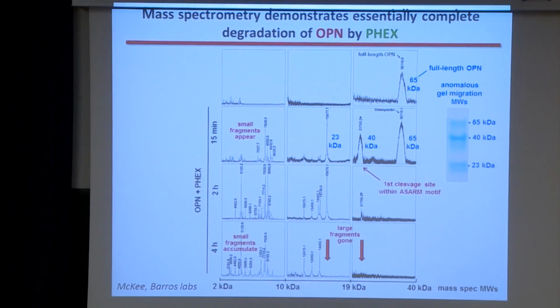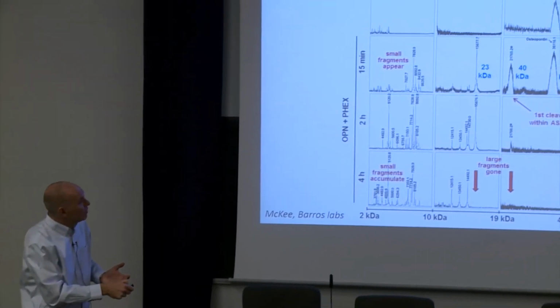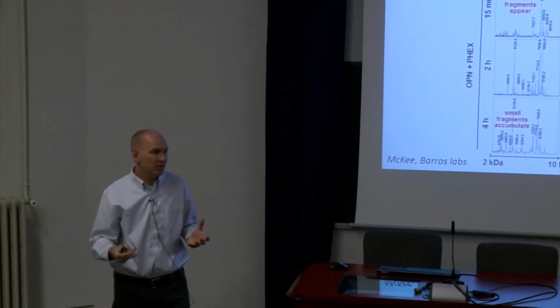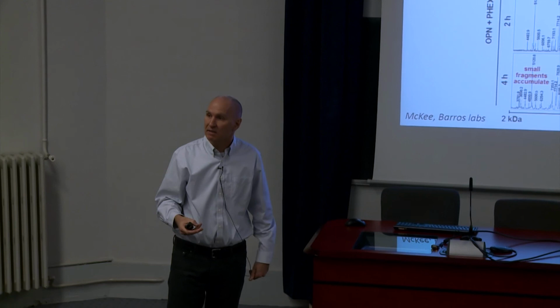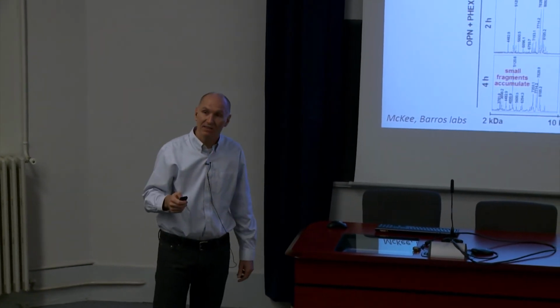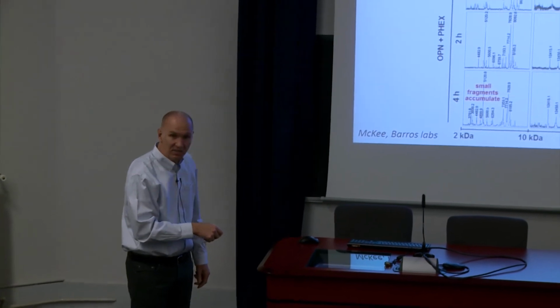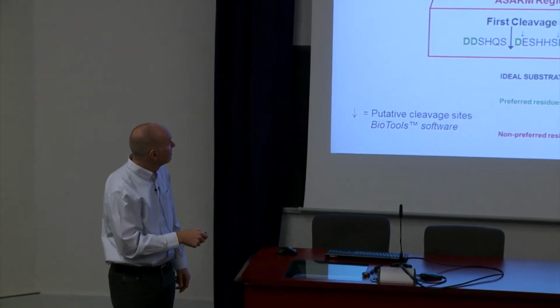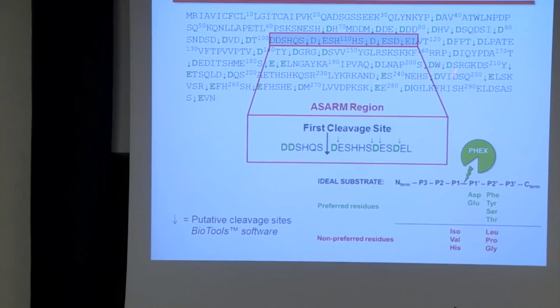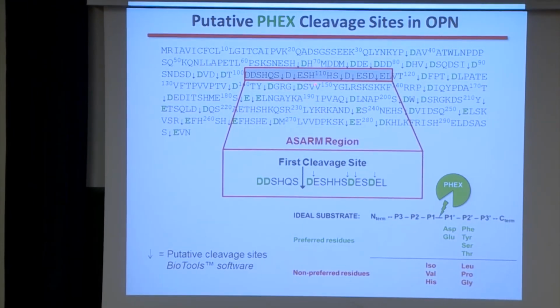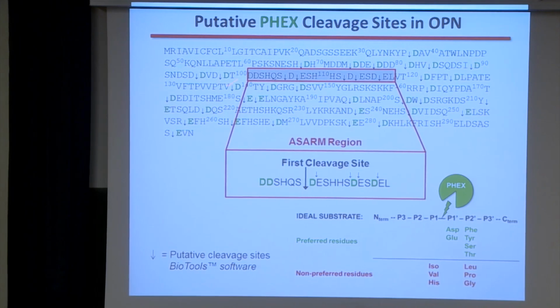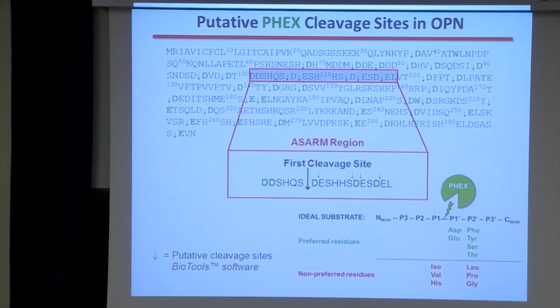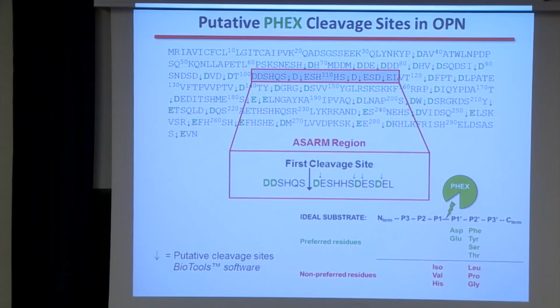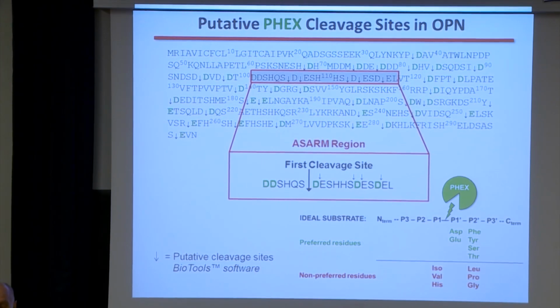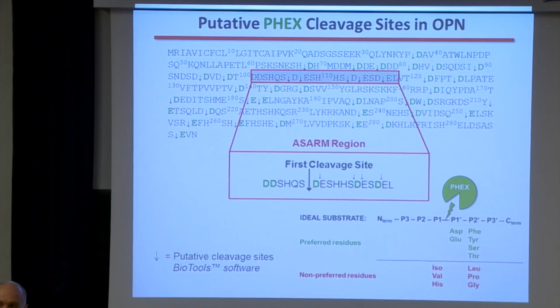So we had an enzyme that could degrade one of our most potent known inhibitors in extracellular matrix biology. And not only degrade it in one place, like enzymes usually do, but degrade it into dozens and dozens of tiny little peptides. In fact, the potential cleavage sites are all over this molecule. The first cleavage site actually occurs in the ASARM peptide, but they're everywhere. These little arrows are all potential cleavage sites based on the substrate specificity requirements for the enzyme. So this enzyme was exhaustively destroying a mineralization inhibitor.